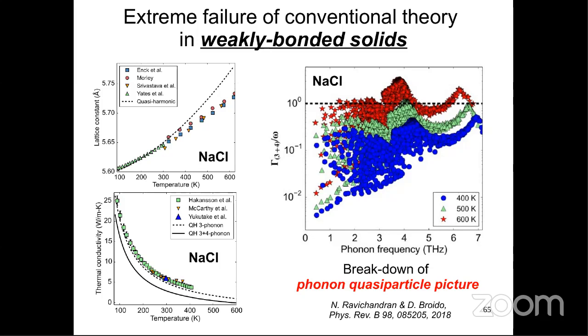Okay, so you mean to say the boundary determines the scale, and essentially the 4-phonon scattering is no longer the limiting factor. That really depends on the material and temperature, right? If you go to low temperatures, and if you take diamond, the mean free path is several millimeters long. But if you take sodium chloride at 600 Kelvin, the mean free path is a few nanometers. So if your device is comparable to that mean free path, it will be affected by diffuse scattering at the boundary. Good. Thank you.